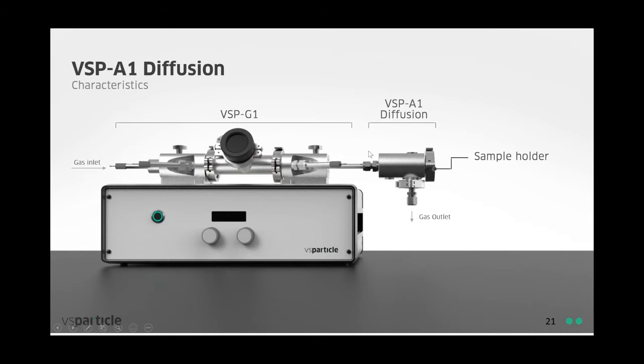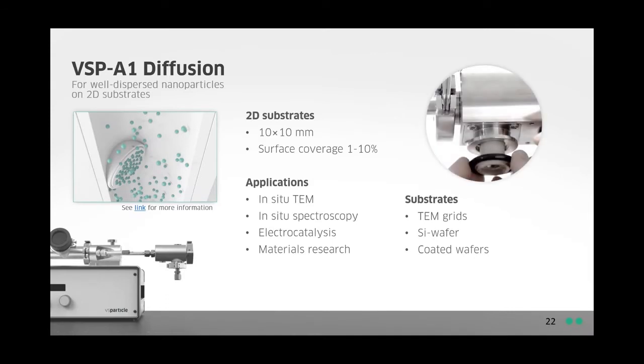The A1 connects directly to the G1 using a Swagelok connection. The A1 diffusion accessory is compatible with flat or 2D substrates with a maximum size of 10 by 10 millimeters. We're able to obtain surface coverages between 1 and 10%. We see it being relevant for in situ TEM, in situ spectroscopy, electrocatalysis, and material science research. Common substrates used are TEM grids, silicon wafers, and coated wafers.